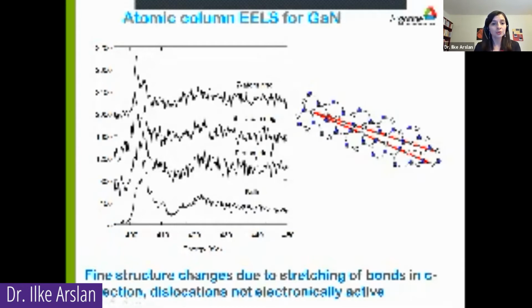And then as you move within this stacking fault from something that looks bulk-like, this 9-atom core, and get closer and closer to the 7-atom ring, the other end, dislocation core, other end of the stacking fault, you see that the atoms are coming closer together. And so what's happening is that they are separating further apart in the Z direction.